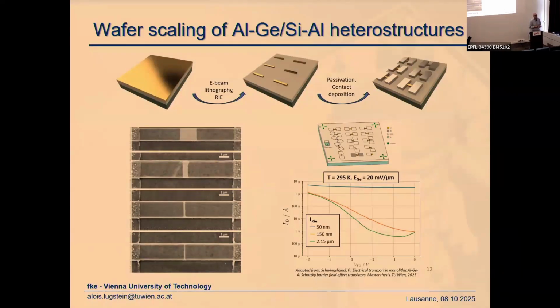We have nice quantum devices. Anyway, this handling of the nanowires is laborious, very time consuming, and not scalable at all. So we tried to transfer this process to a germanium-on-insulator wafer. That means we started with a thin layer of germanium on top of an oxidized wafer. Now we patterned the nanowires or the nanosheets, added the aluminum contact, did the annealing, and here you see some examples. Indeed, it's one and the same device after different annealing steps. So it works the very same way as for the nanowires.